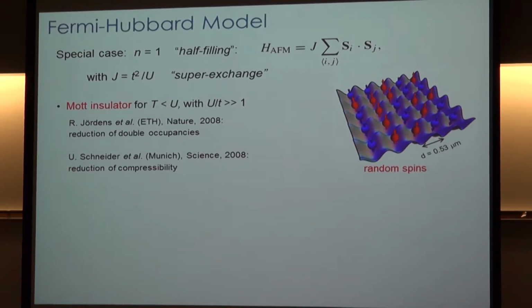So it turns out that if we consider just a particular density, which is what we call half filling, which is 1 atom per site, that Hubbard model maps into a Heisenberg antiferromagnet. And this Hamiltonian can be solved exactly. So this is a very special case. This is the special case where we're at half filling at this particular density. And in that case, we can solve it. We find that there's a particular energy scale which is relevant to forming antiferromagnetic order, and that's called the super exchange energy scale. So the super exchange energy scale, the second order term, involves hopping onto one site, interacting with a particle, and then hopping back off of it again.